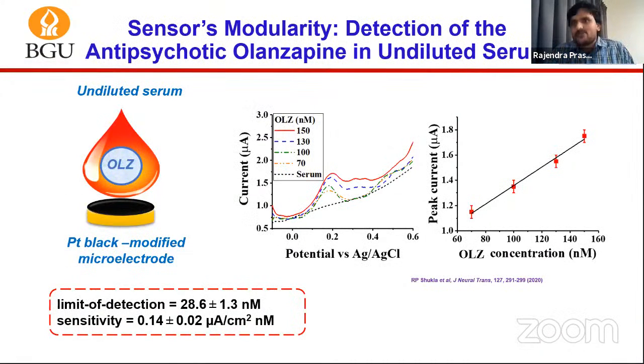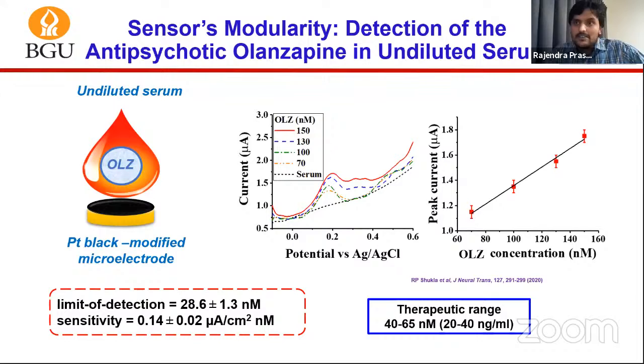We were not limited to clozapine only because there are other classes of antipsychotic drugs that are redox active. We also explored the platinum black modified electrode for the detection of olanzapine. Here we found a very nice performance, and we detected olanzapine below its therapeutic range, with a limit of detection around 28.6 nanomolar in undiluted serum samples, in a 20 microliter sample volume.